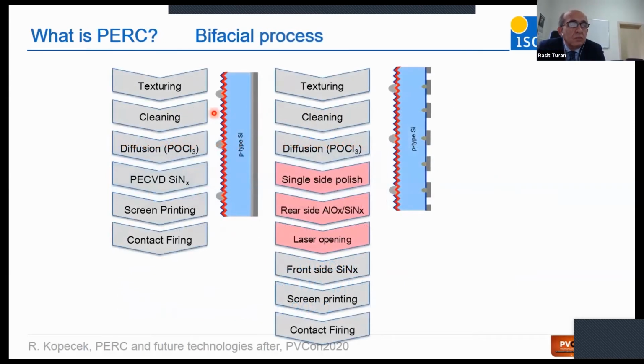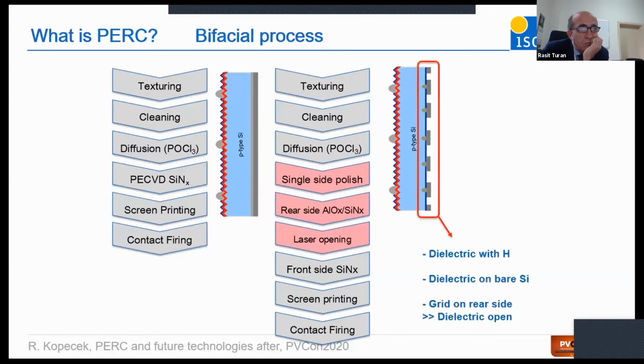So if you want to compare PERC with a standard aluminum back surface field technology that is now washed out of the market because of the low efficiency potential, there are, let's say, only 3 important steps that were implemented on the rear side, which was single side polishing, then deposition of a dielectric, which is now mostly aluminum oxide and silicon nitride, which was then opened by laser. And here you can see that actually the rear side looks very much different from the rear side of an aluminum back surface field. That means you were implementing dielectrics with additional hydrogen included, then also depositing or processing dielectric on bare silicon, and the grid was open. So actually the dielectric was also open for some degradation mechanisms.